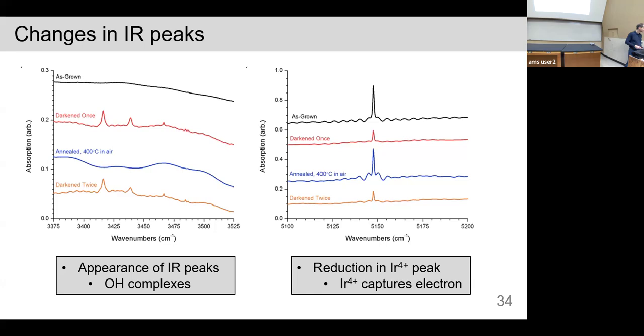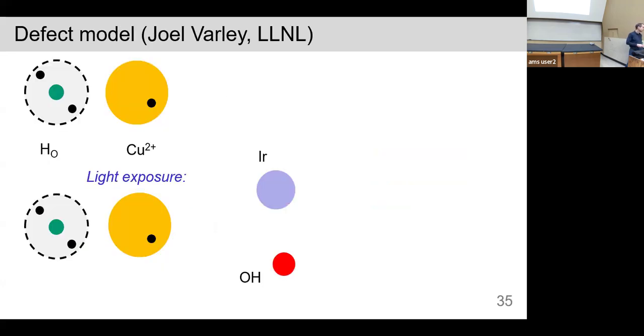Okay. So what's going on? This is a little more complicated, but it's a similar story. So we start with this hydrogen substitutional. Again, that's a proton and 2 electrons on the oxygen site. But next to that is a copper atom. They would call it copper 2+. Now, when we expose it to light, that excites the electron. The electron gets captured by the iridium, and that causes the iridium peak to go down. All right. Well, now this new charge state is unstable, so the proton leaves and attaches onto an oxygen atom, and that forms the OH infrared modes that we see.